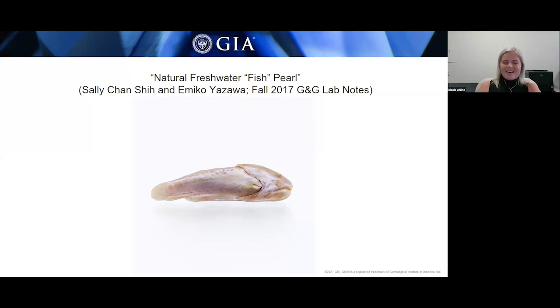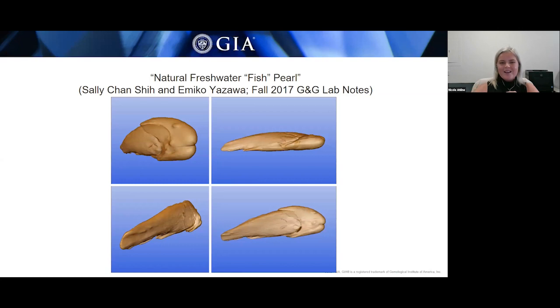The entire nacreous surface was composed of overlapping platelets with no indications of work, such as polishing, nor were there indications of treatment such as dyeing or coating. With EDXRF chemical analysis, there were higher levels of manganese, which supported that this was formed in a freshwater mussel. Using real-time microradiography and X-ray computed microtomography, it revealed clear natural growth structures that conform to the pearl shape. And here's a 3D rendering of the X-ray CT data, showing just the remarkable likeness of a swimming fish.